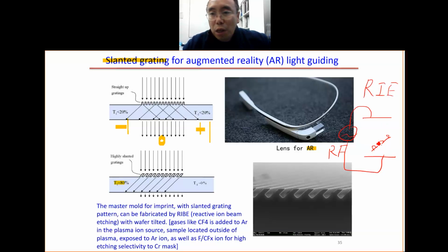It will tell the sample the etching may be slanted etching. But actually this will not work because we have the wafer inside the plasma. It will be negatively charged because electrons move faster. Then the field is still in this direction. The ions like fluorine and argon come here vertically, perpendicular to the wafer surface. So the etching will be perpendicular to the wafer surface. Then you get this vertical etching rather than slanted etching.